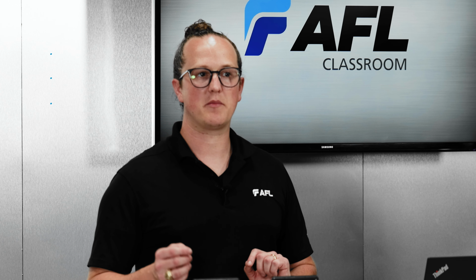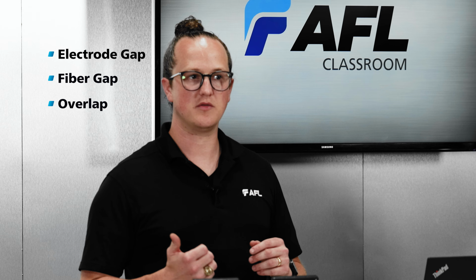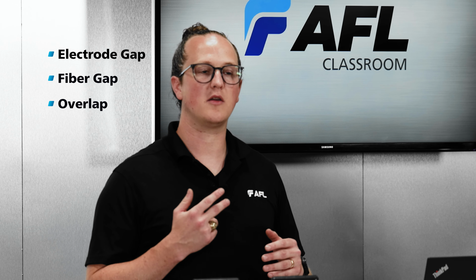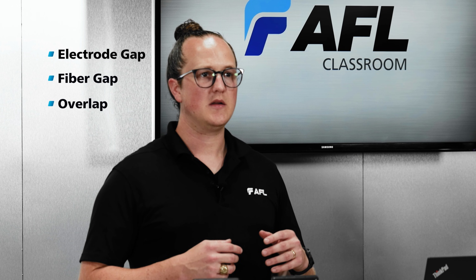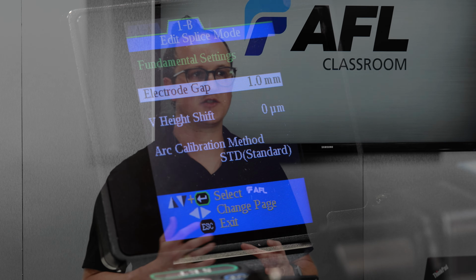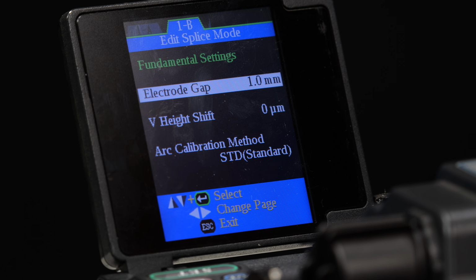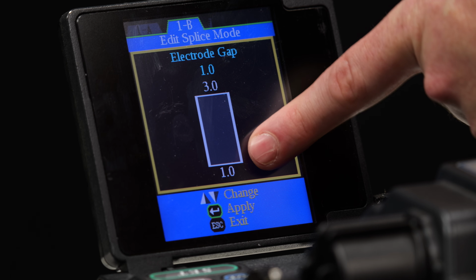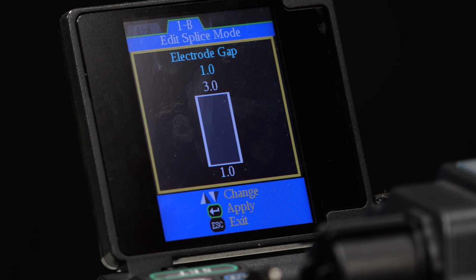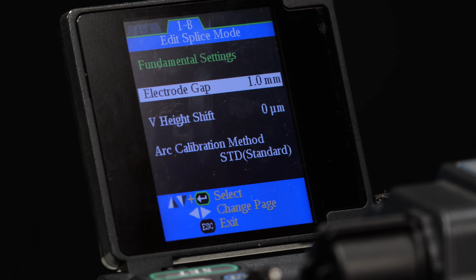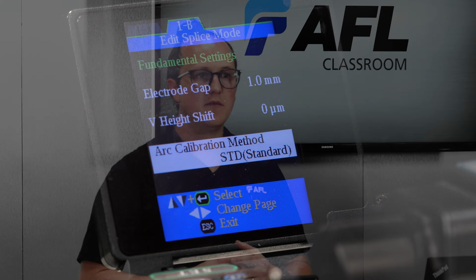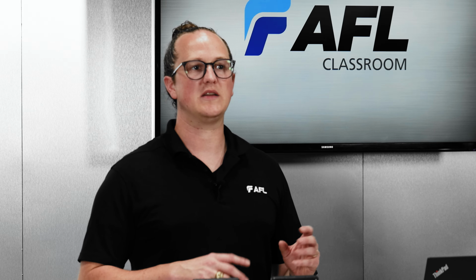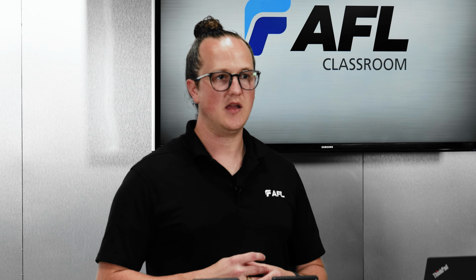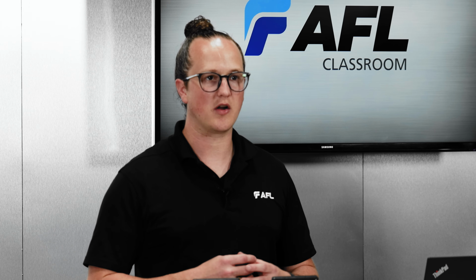After tuning in the prefuse, we can move on to the rest of the splice parameters, but the three key parameters to investigate here are the electrode gap, the fiber gap, and the overlap. As mentioned in a previous video, the electrode gap is primarily a function of the fiber's cladding diameter. So at this point in the optimization, you can tune in the electrode gap if it makes sense to change the size of the heating zone. Keep in mind though, that this will reset the arc calibration's accuracy and require you to use the standard arc calibration method.